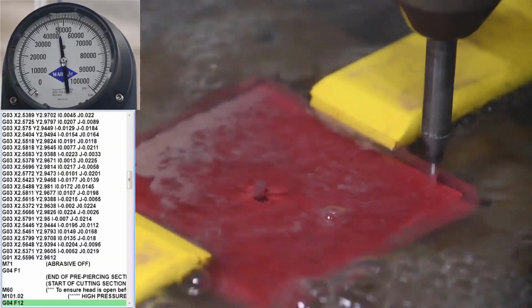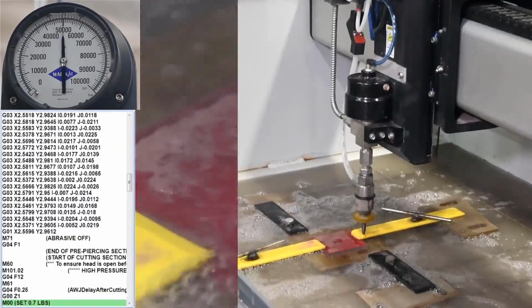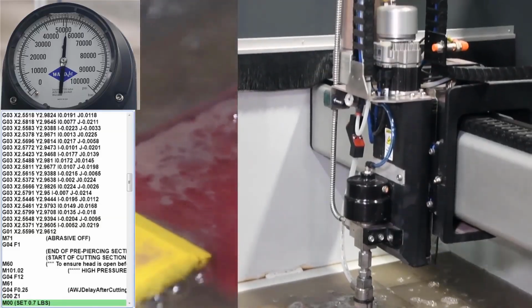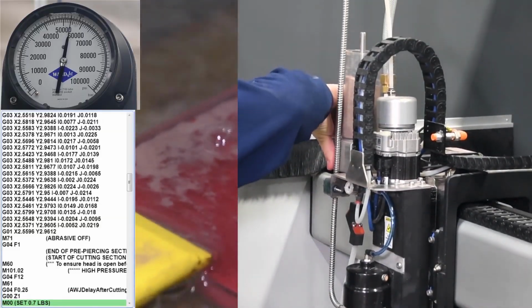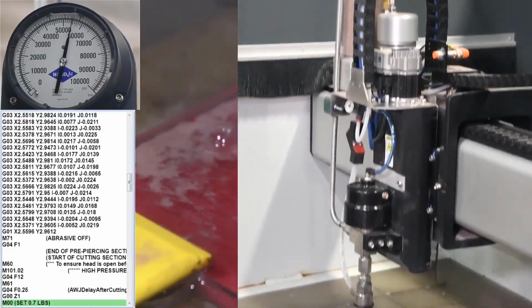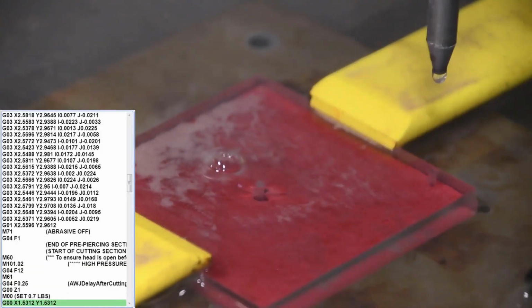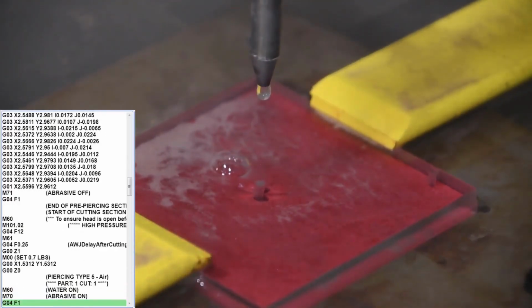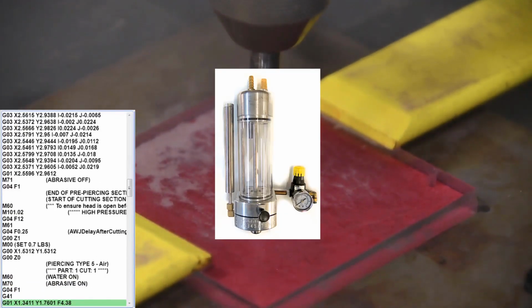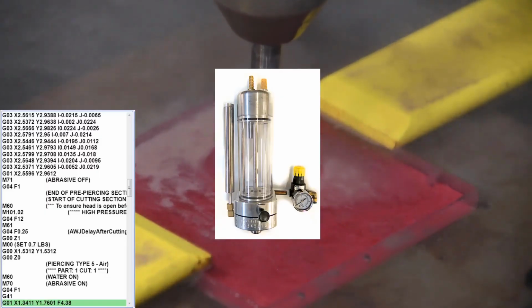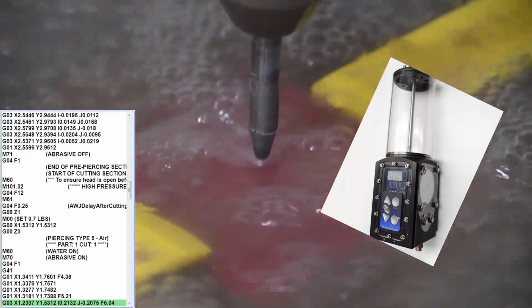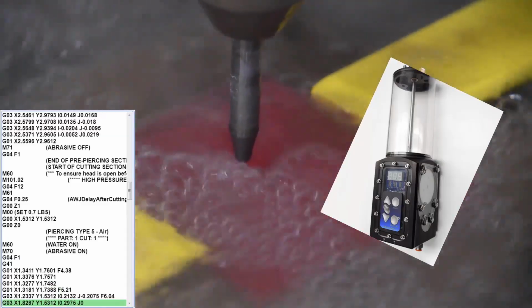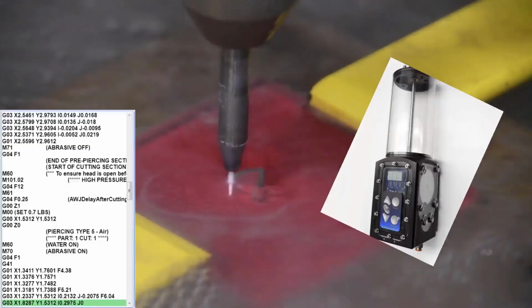For the low pressure piercing, reduce your abrasive flow rate to about half of what you're using for high pressure cutting. Lower pressure creates less of a Venturi effect inside the cutting head and cannot suck as much abrasive into the head. We have both a manual style mini hopper that you see in this video and an automated mini hopper that will change the abrasive flow rate depending upon if the pump is in low or high pressure.